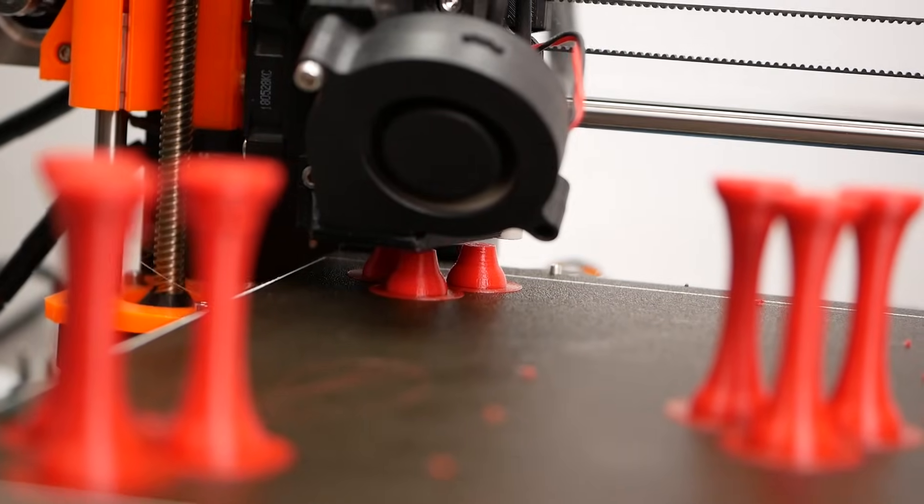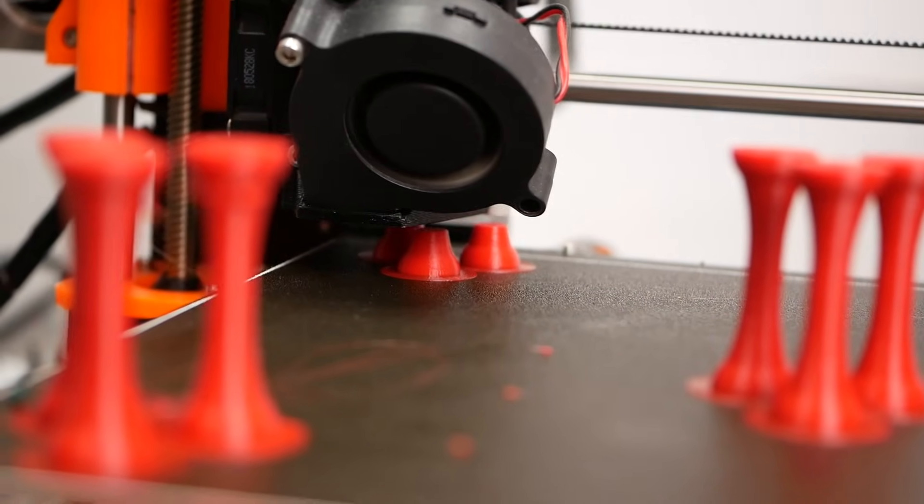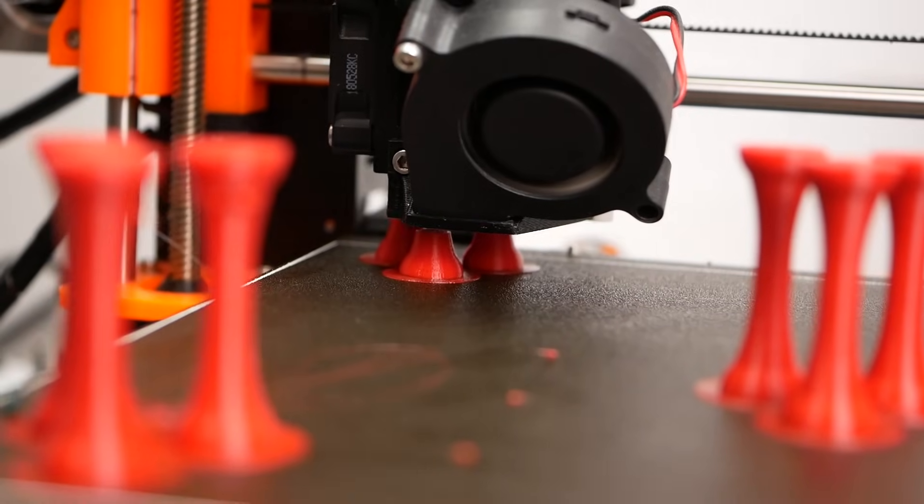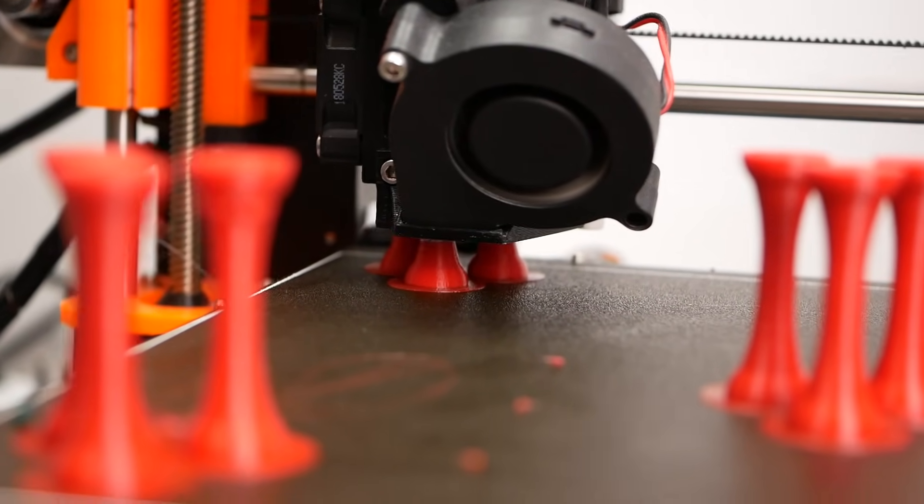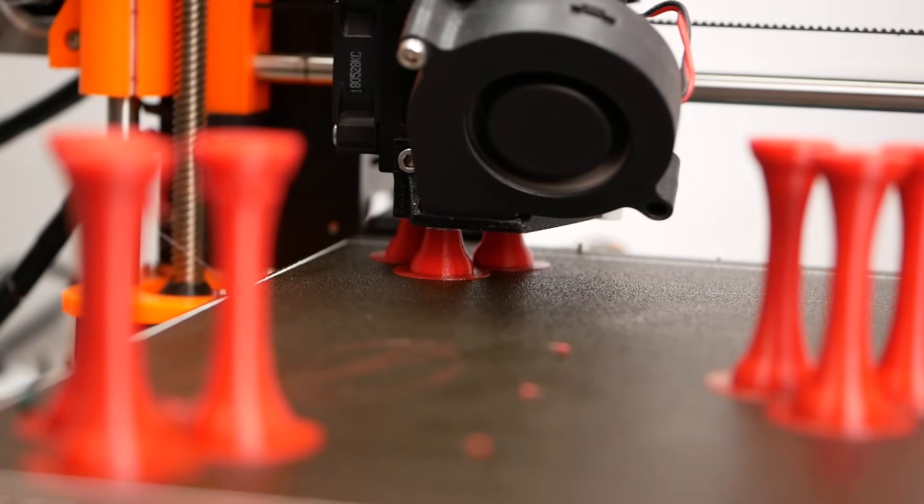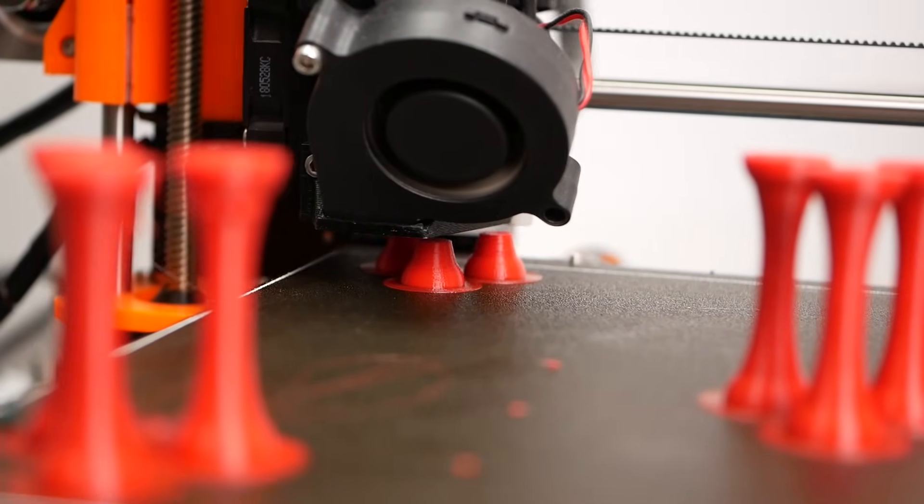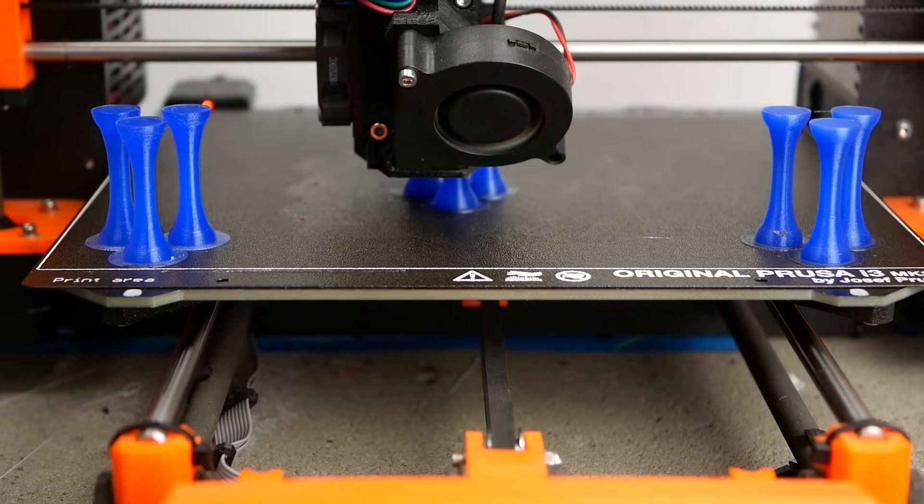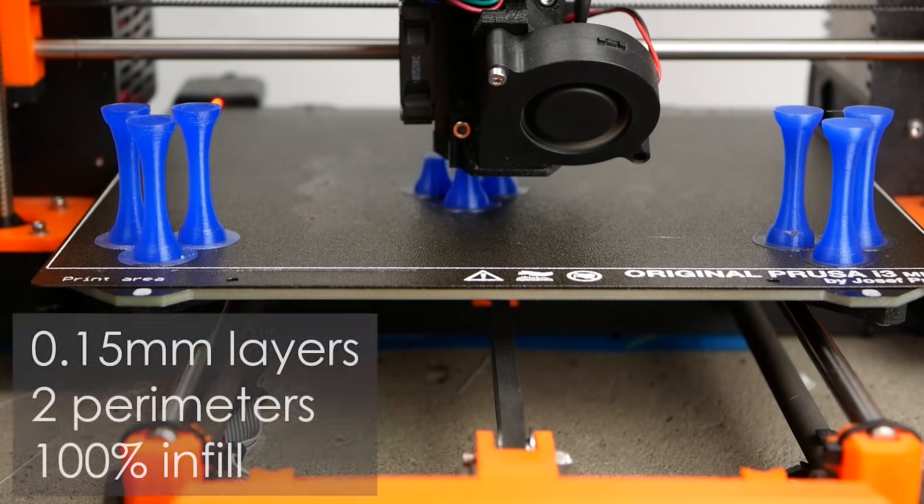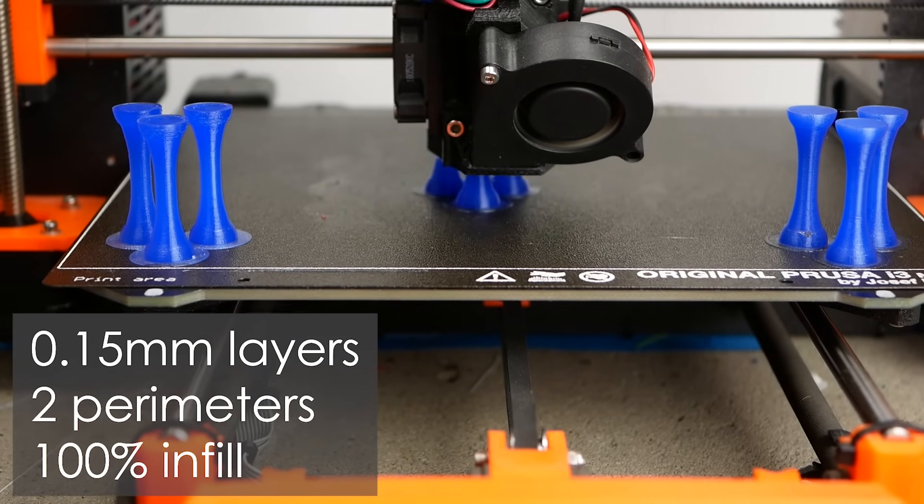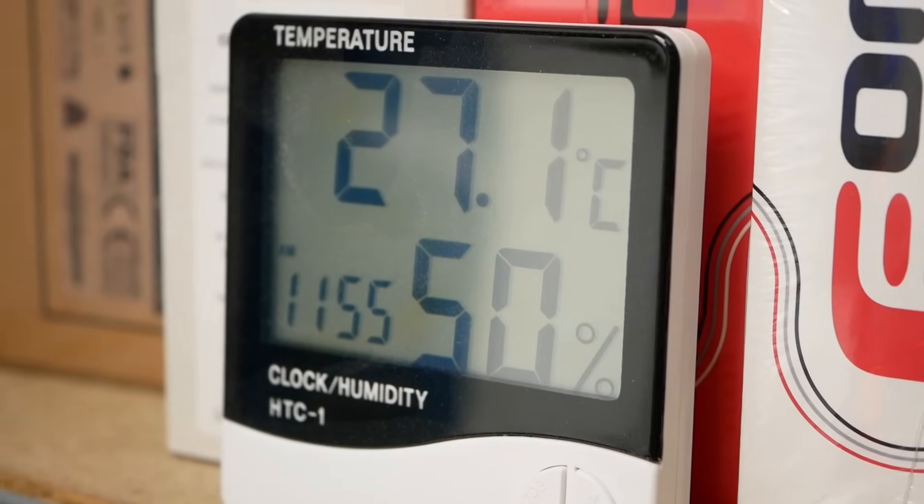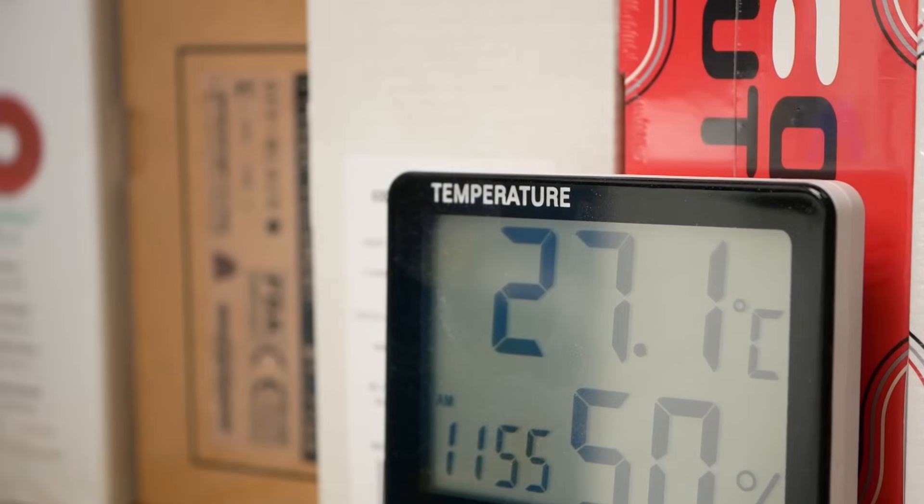Please bear in mind that these set of results are probably not 100% true for any other filament manufacturer and printer because slight changes in the setup can have a huge impact on the results. So, use this more as a guideline and look at the trends. I printed all of the samples on my original Prusa i3 Mark 2.5 at a layer height of 0.15mm with two perimeters and 100% infill. At the time of printing it was summer and I had between 26 and 27 degrees centigrade in my office.